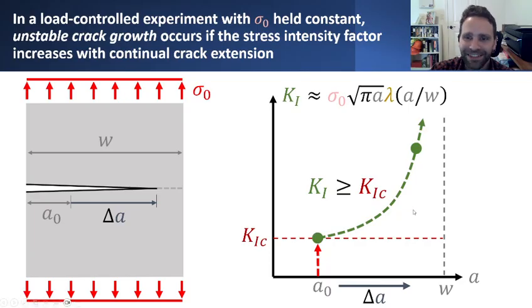Now, you might not necessarily have the time to go through this as it's actually happening in real life. If you were to run this experiment, what you'd find is that the crack would extend almost instantaneously through the entire specimen. And it would seem as though everything happened all at once. There was no cyclic feedback loop of crack growth leading to increase in stress intensity factor. It all happens very suddenly. And that behavior of the crack extending and basically failing the entire specimen instantaneously in this very dramatic way is what we might refer to as unstable crack growth.